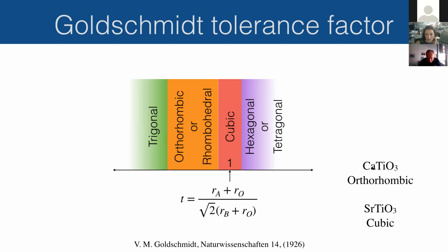So another example, the same as before. Calcium titanate is orthorhombic, strontium titanate is cubic. So calcium titanate would find itself here. And if you want to make the structure more cubic, you substitute calcium for strontium. Strontium is larger than calcium, so you have an increase of the A-site radius. So overall T increases and you move into the cubic phase. So it's very well explaining at least these 2 compounds and many others.